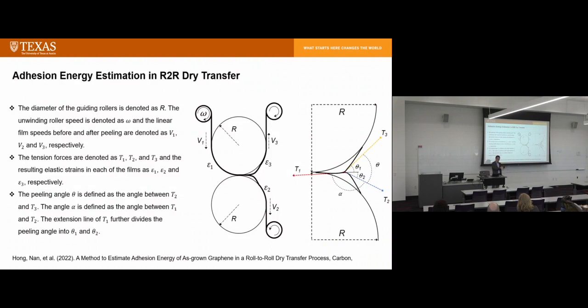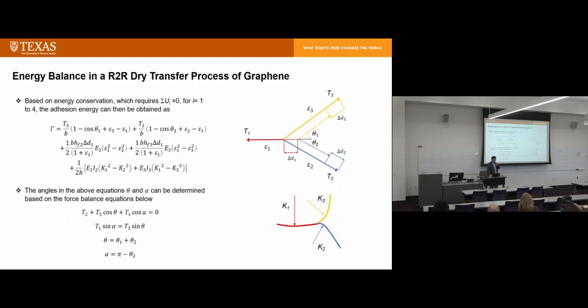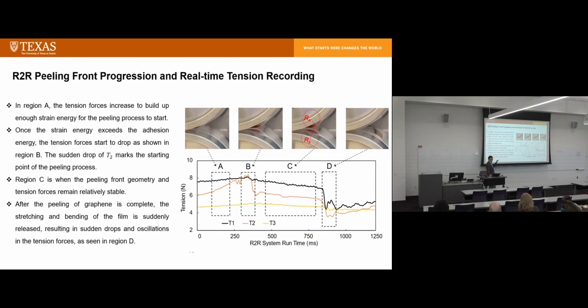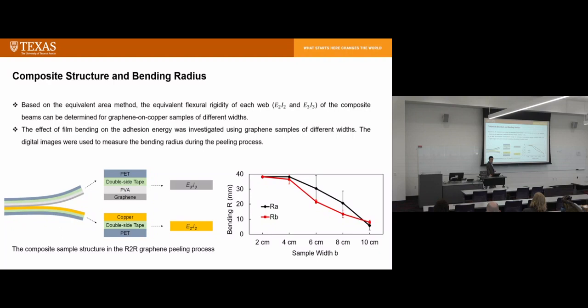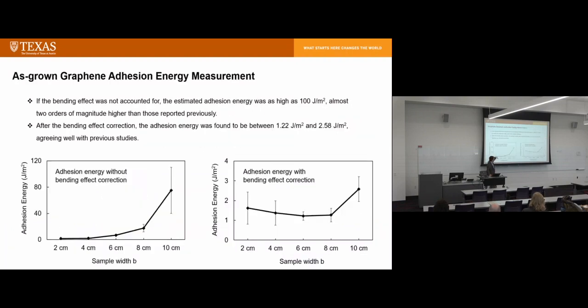So we also did adhesive energy estimation during the R2R process. We can do similar modeling, and then during the process, we measure tension. We can estimate the adhesion energy also, just based on the tension measurement during the R2R process. And that's important because, in the beginning I told you we're not only interested in peeling graphene, we're also interested in peeling printed electronics. So inline in situ estimation of transfer adhesion energy is important for control. So we were able to estimate the adhesion energy by correcting for bending energy. There's a lot of process going on in the peeling process. So the result we get is actually similar to the result we get from the blister test. So that's another way of estimating adhesion energy.